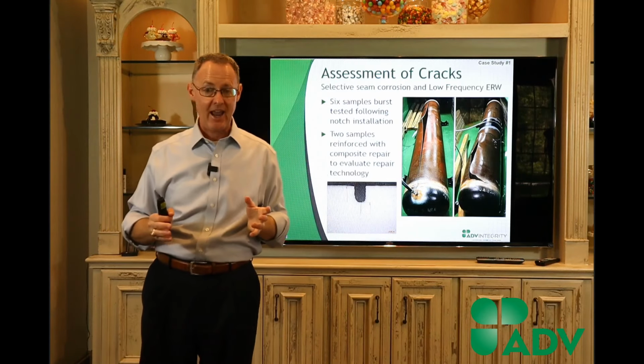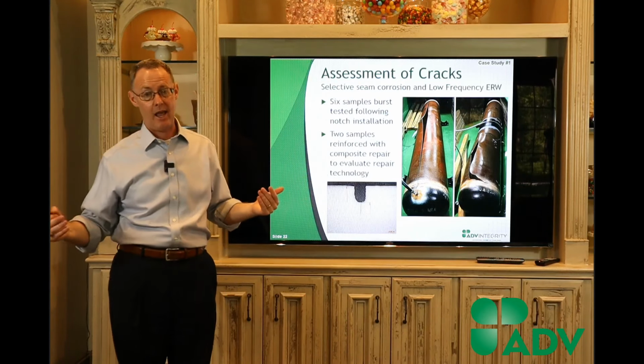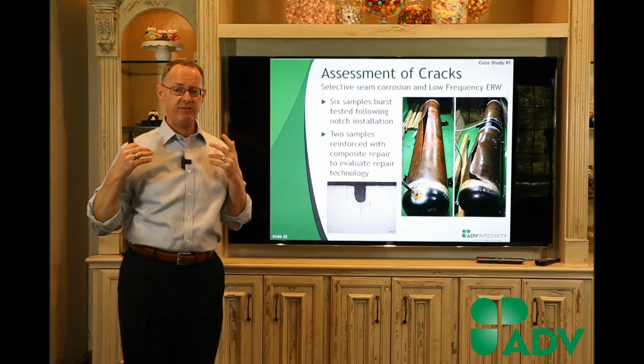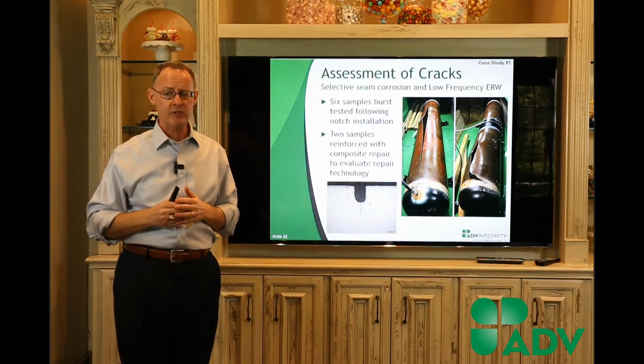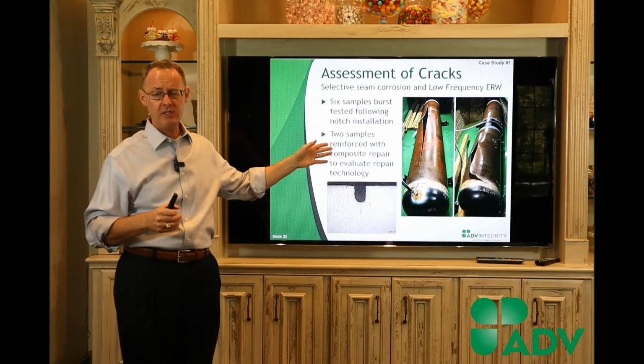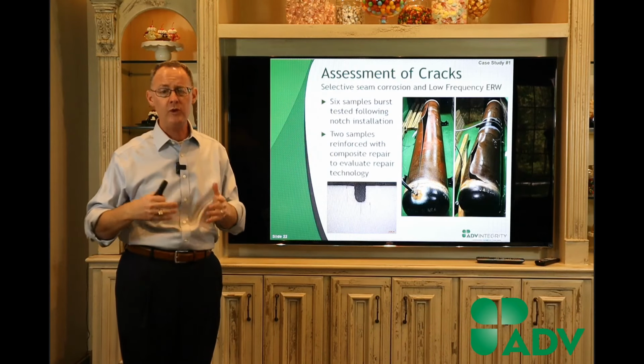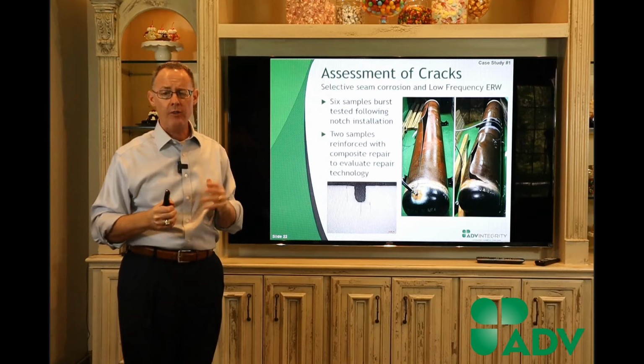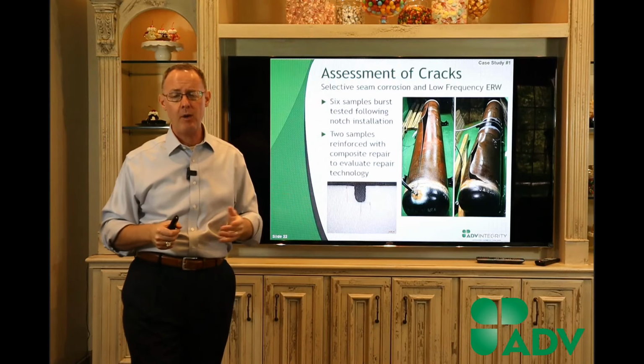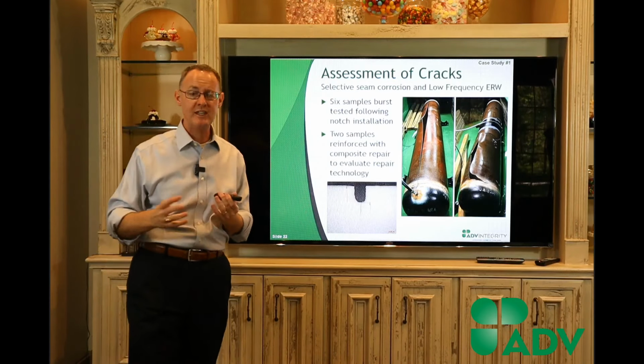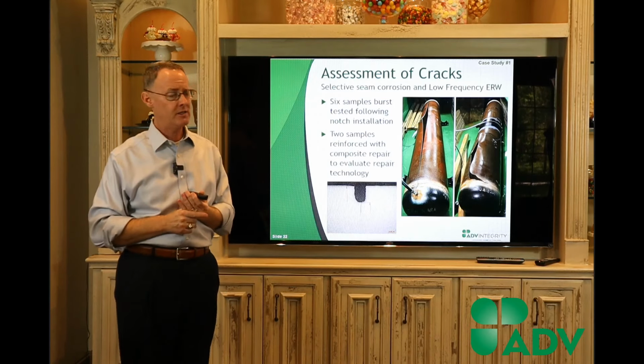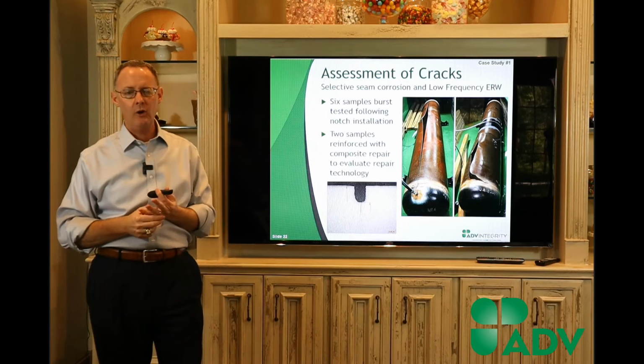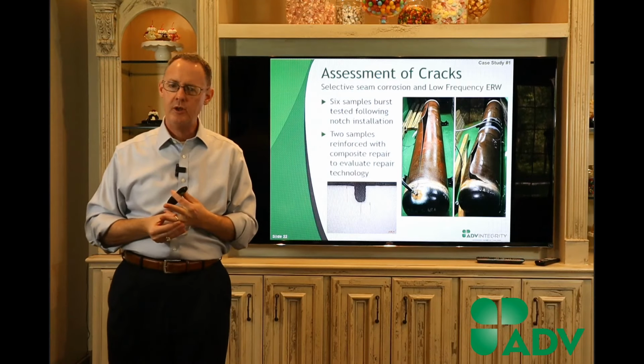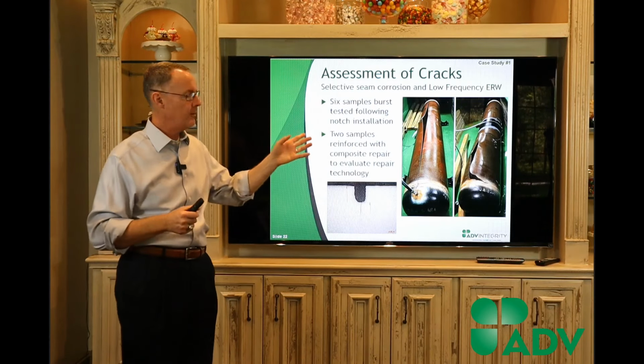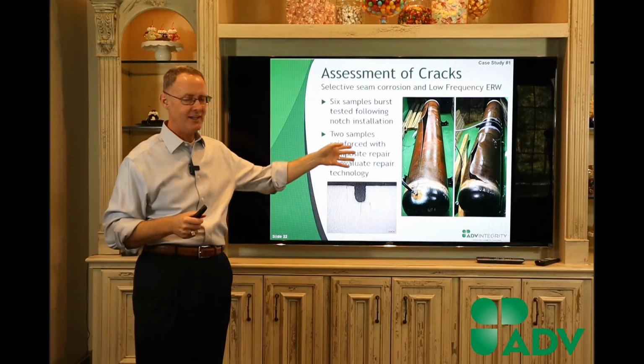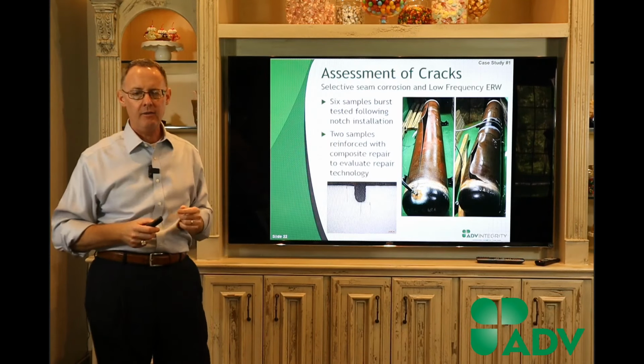If we tested with gas, we would have run all the way through the end caps. And so when pipelines fail and they're under high levels of pressure, this is what happens potentially in a low frequency ERW seam if you get a fracture to run. On the right side, we tested a composite system. This is actually a Milliken or CSNRI's Atlas carbon epoxy technology. We've tested it a lot, reinforcing cracks with extremely good results. And so we had the same defect there, and what you notice is the fracture initiated outside the notch crack